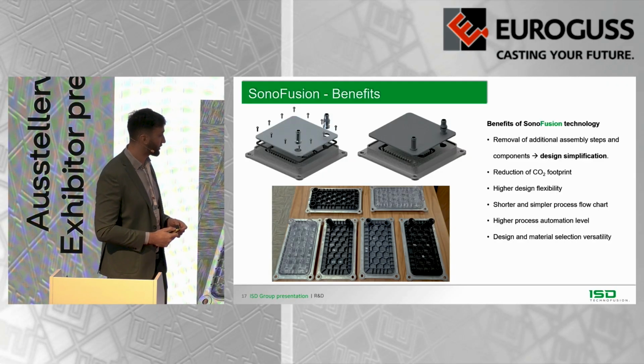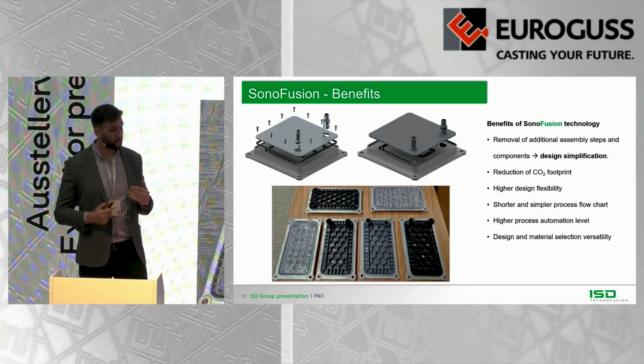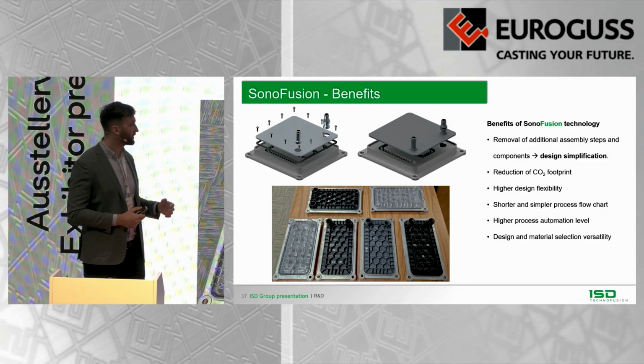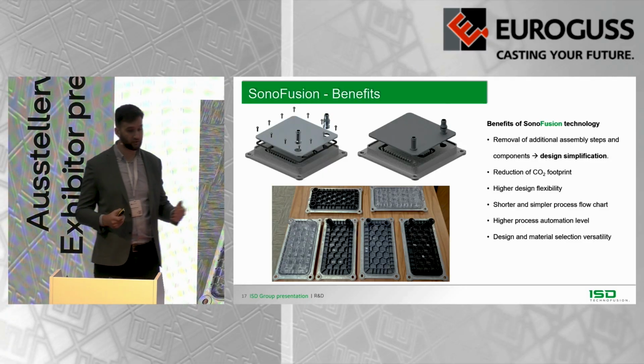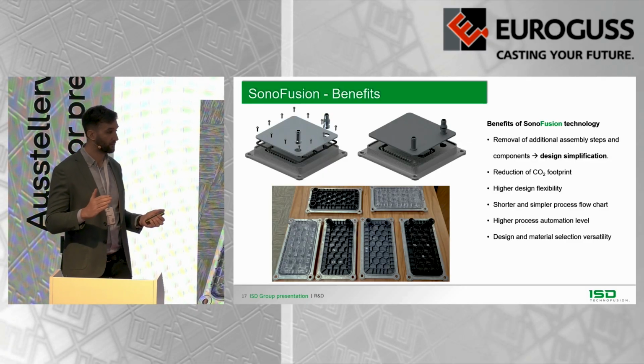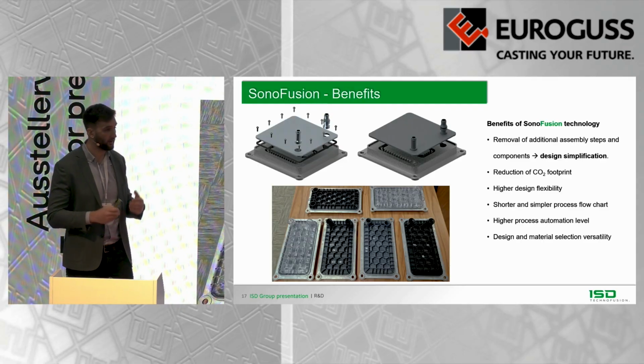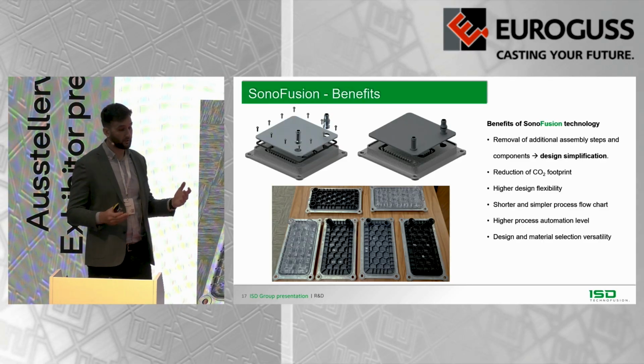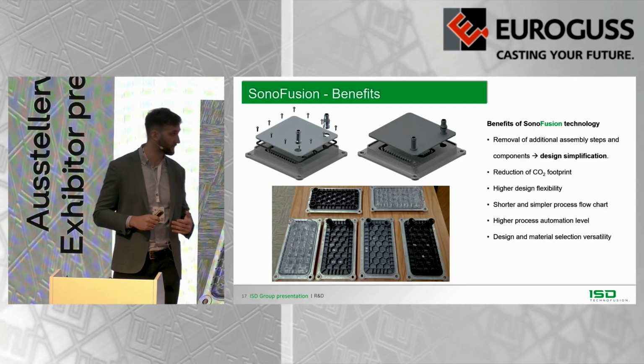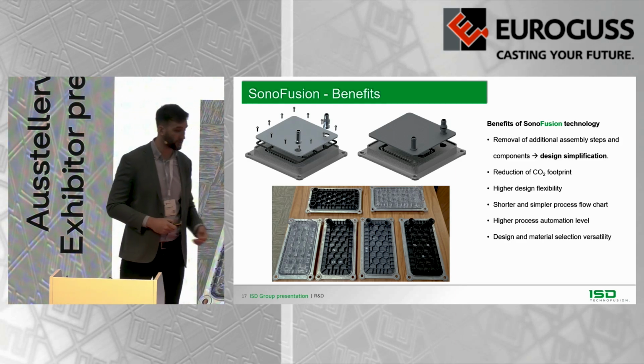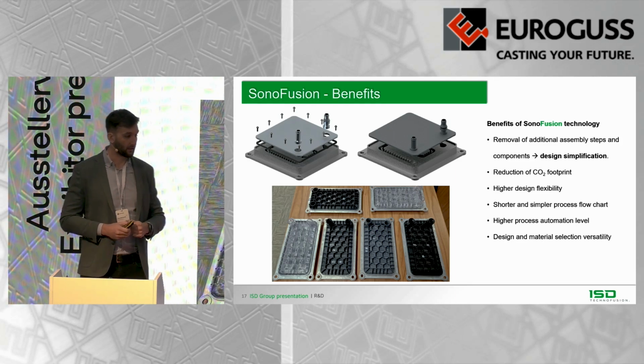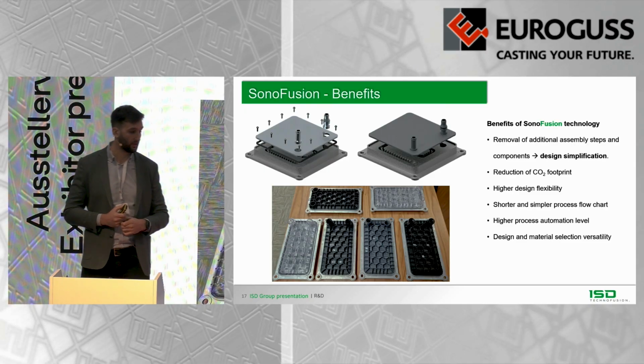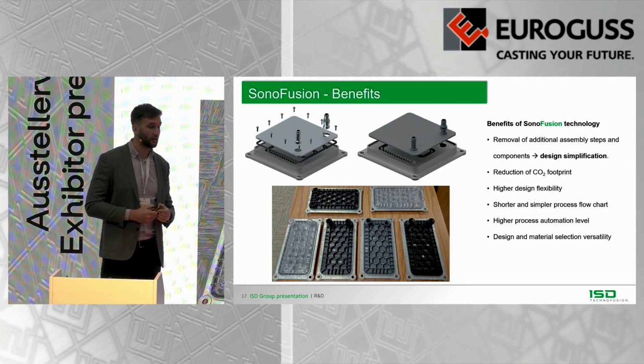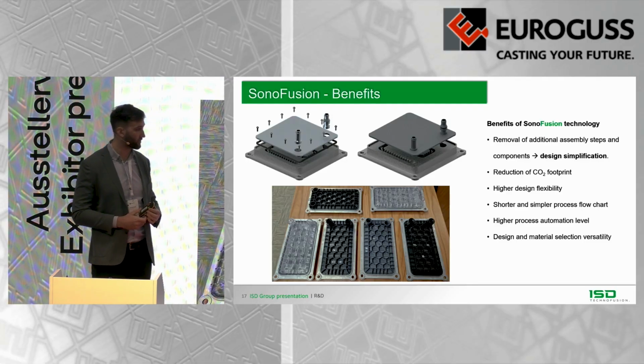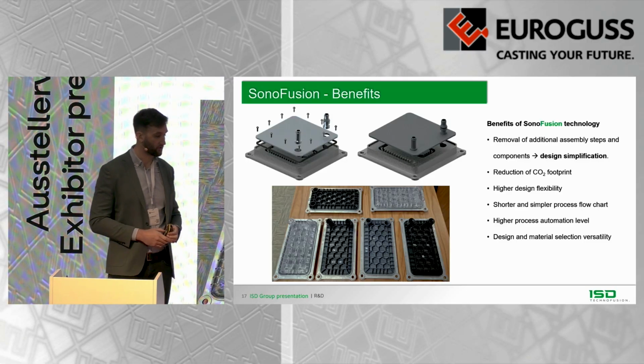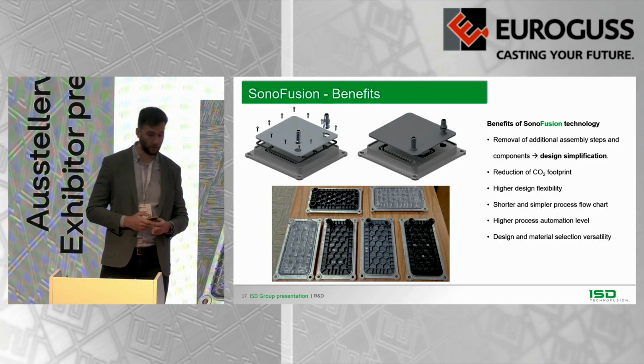And another benefit for sure is also the design and material selection versatility, because you don't really need a high technical polymer if your application, let's say, only needs up to 50, 60, 70, or 80 degrees Celsius. You can take a very cheap technical polymer, or if you have temperatures up to 140, 150 degrees Celsius, you can use a PPS, which is a high technical polymer with high operating temperatures. So you're very versatile in terms of what you want to achieve. We can then adjust the material selection and obviously also adjust the design itself to meet your requirements.